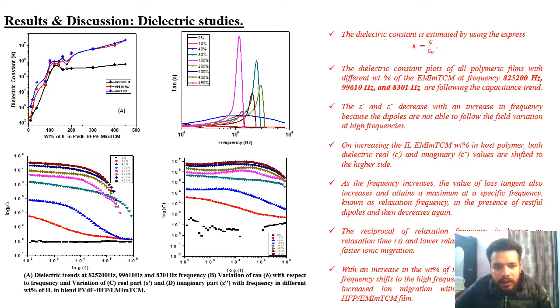Tan delta is the dielectric loss. So here you can see that while increasing the frequency, the tan delta is also increasing, and then it attains a maxima at a certain frequency, and then it starts to decrease again. This maxima is known as the relaxation frequency, and the opposite of it is known as relaxation time. So the lesser the relaxation time, the greater the ion migration inside the film. Here we get the lowest relaxation time, in the order of 10 to the power minus 7, for the 200, 400, and 300 films. So we can say that these have the highest ion migration in them.